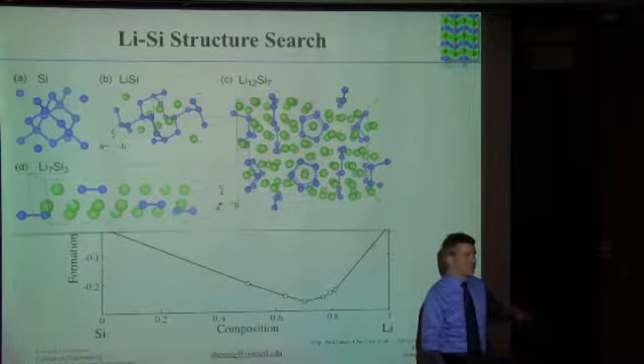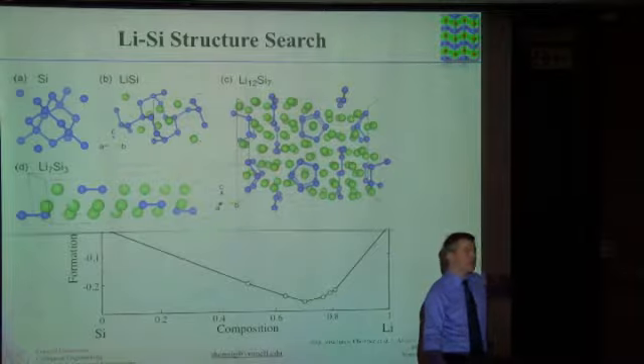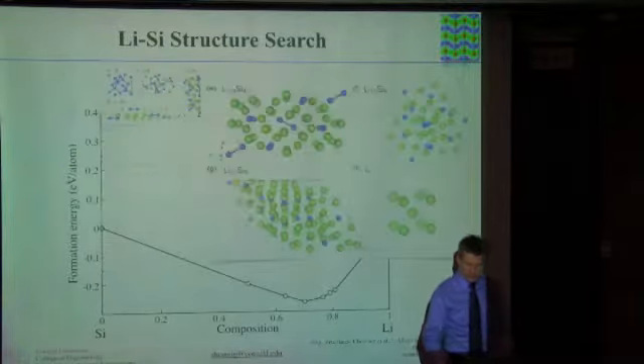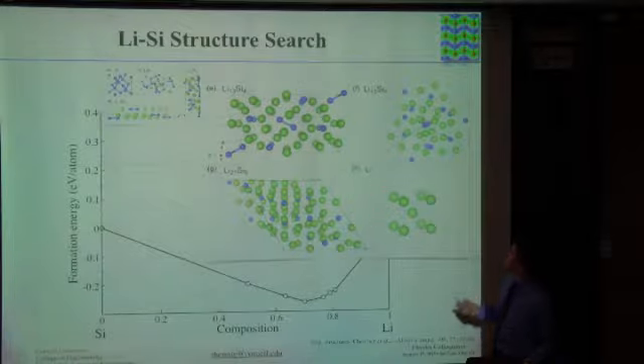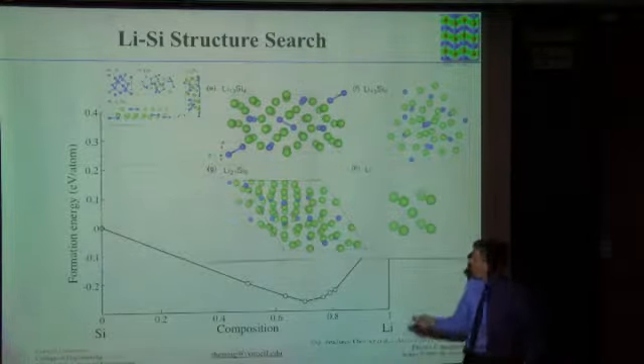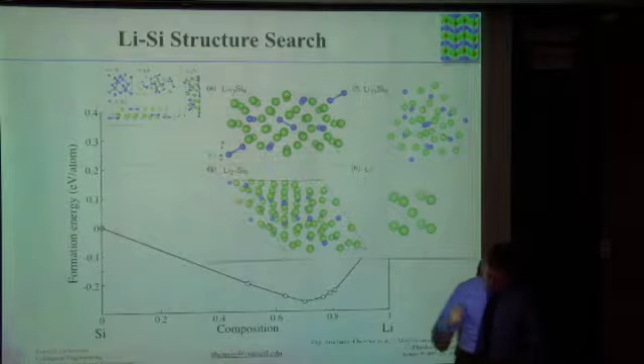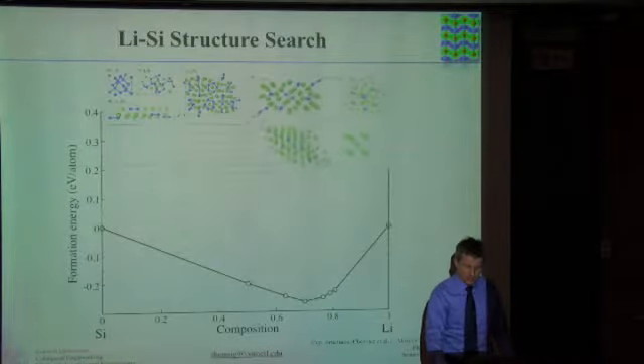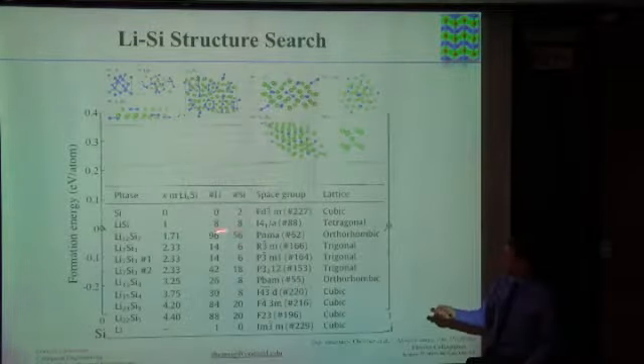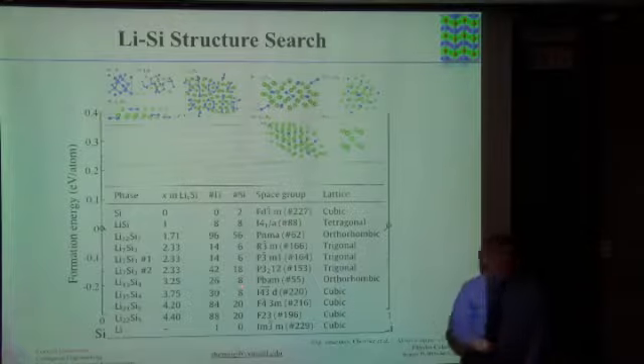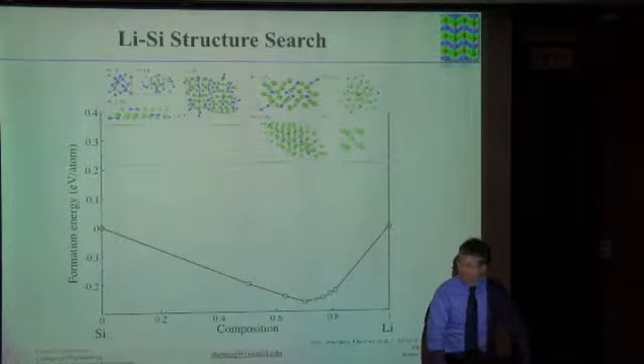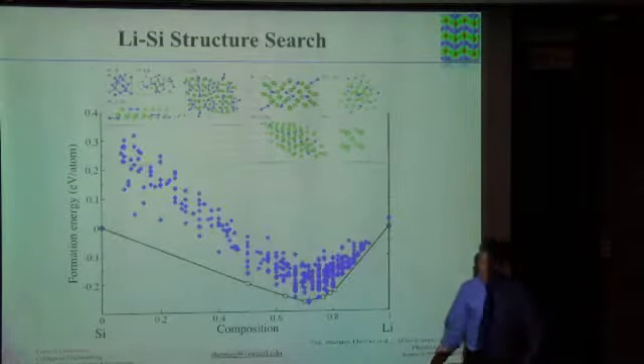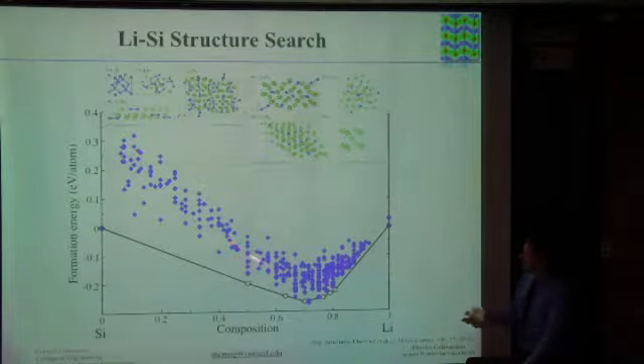So we limit ourselves to structures which are less than 20 atoms and try to find, really, can we describe the overall energy landscape somewhat accurately. Here's those, then the lithium-rich side shown on this side. Again, a lot of complicated structures until you reach BCC, room temperature lithium. Here's a table of crystal structure, and you see there's a large number of atoms in some of these crystal structures, so we're not trying. So instead, what we do, we just run with small unit cells, and here's our genetic algorithm results, and here are the low energy structures we find.